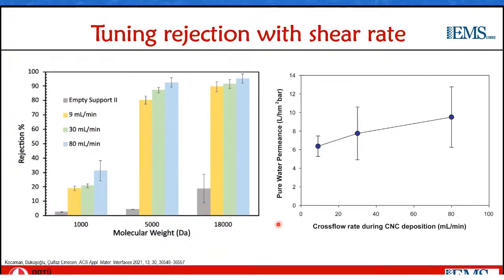And lastly, I want to mention that the permeance of these CNC membranes is quite reasonable compared to the rejection behavior they show. So compared to a tight ultrafiltration membrane, molecular weight cutoff, let's say from around 5 to 20 kilodaltons, for all these membranes the pure water permeances are quite reasonable. I should also note here that the CNC layers that we use as membranes here are not as thin as they can potentially be. For ease of analysis, especially the optical analysis, the thicker the CNC layers, the easier to distinguish what's happening. But in principle, these layers can be made thinner by simply adjusting the CNC concentration in the suspensions or the transmembrane pressure, and this would be expected to increase the permeance of these membranes.